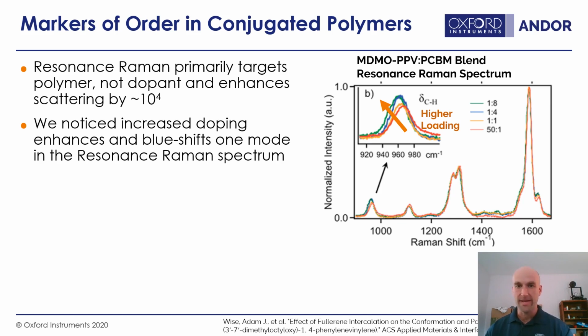So, we're stuffing more and more of these soccer ball looking molecules with side chains or with solubilizing groups into there. And something is happening. Surprisingly, the resonance Raman spectrum doesn't change that much. We don't get big frequency changes. We don't get huge changes in distribution of intensity. Just this one peak at around 960 wave numbers. And you can see the high resolution Raman up there showing a small shift, but most visibly an increase in intensity. So the question is, where does that come from?